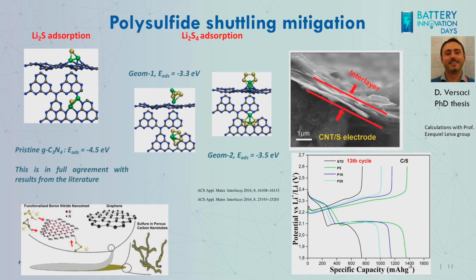In practice, the structure is similar to graphene, but with carbon and nitrogen there. You can see here in a simple graph that the standard material, the one without the interlayer, which is the black curve, performs much worse than the one with this.